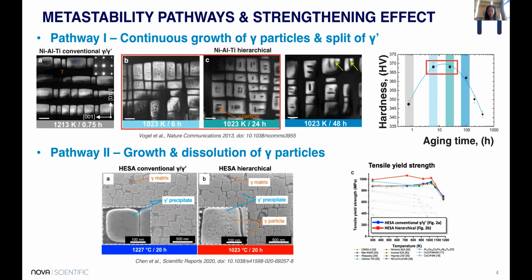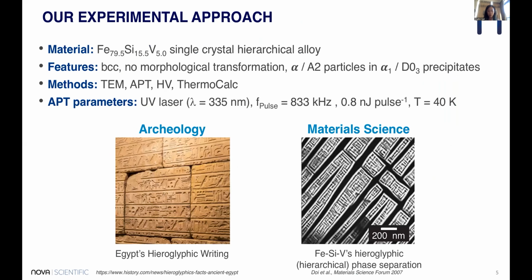Research has already been done on hierarchical microstructures in FCC-based alloys, where in most cases, hierarchical particles first appear as spheres and then undergo a certain evolution. The material we study here is an iron silicon vanadium single crystal alloy with a BCC structure. In this alloy, additional particles appear as plates already after a very short aging time.